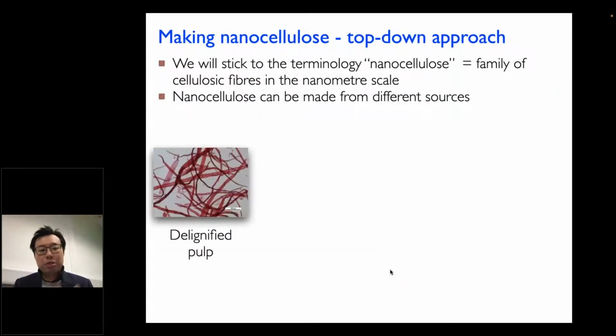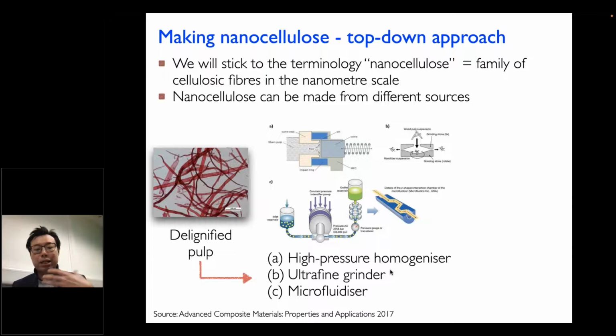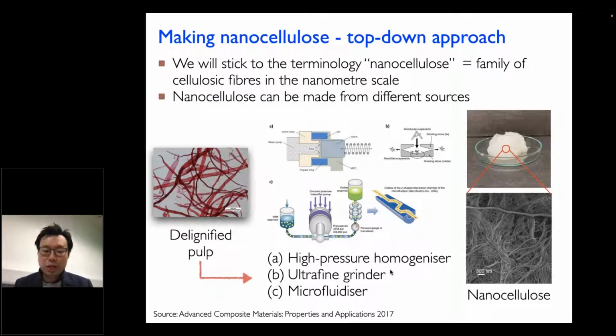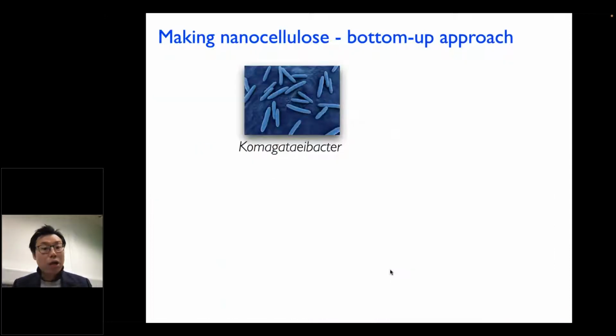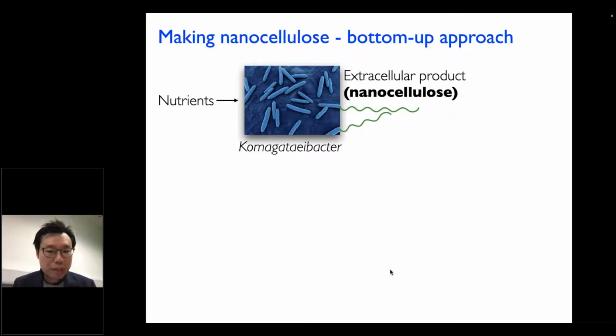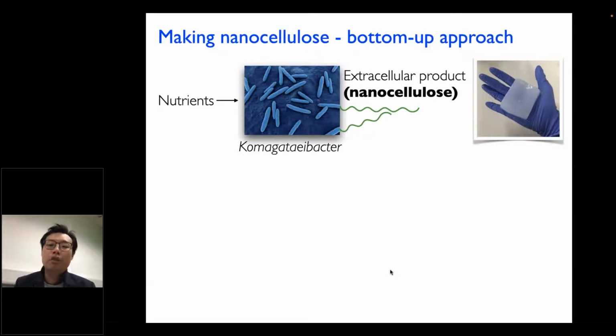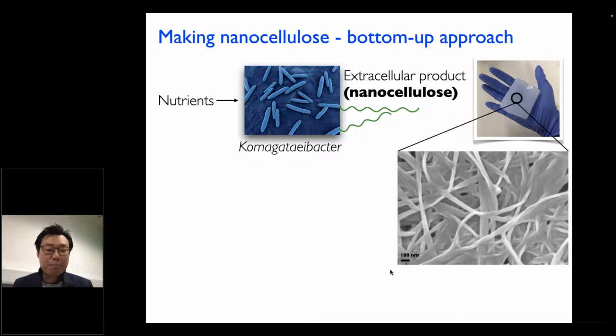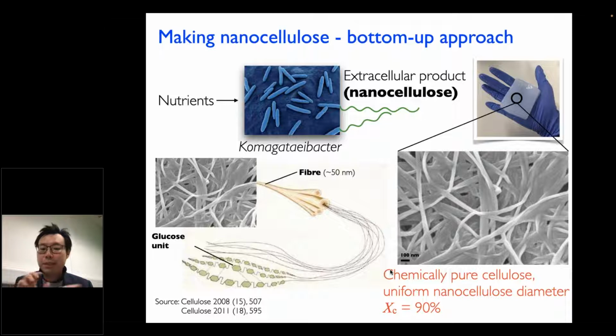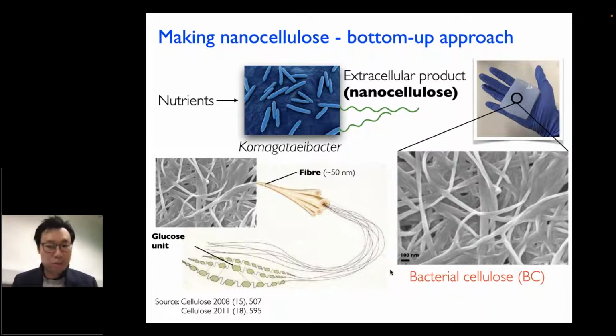So there are two types of cellulose nanomaterials. You can take wood pulp, you pulp it. After you delignify that pulp, you pass it through high pressure homogenizers, grinders, microfluidizers to produce this wood-derived nanocellulose. Typically in the literature, you call these things cellulose microfibrils or nanofibrils. You see the SEM images on the bottom right corner. Or you can actually grow this cellulose yourself through bacteria. You feed bacteria nutrients, bacteria is happy, start to produce something for us, and that something is that little gel on the top right hand side corner. It is actually a fibrous net of sort of 50 nanometer fiber width, and it is chemically pure without hemicellulose. These things are very crystalline, 90% crystallinity, and in the literature you see them known as bacterial cellulose or BC in general.